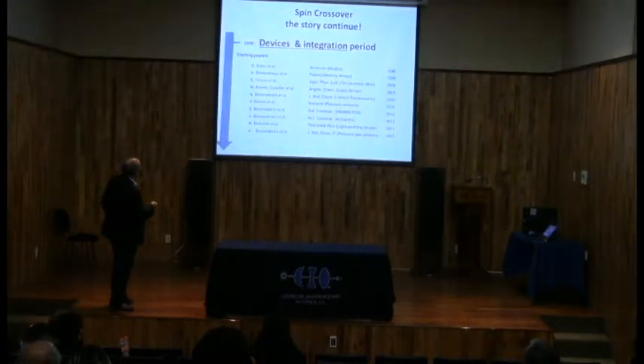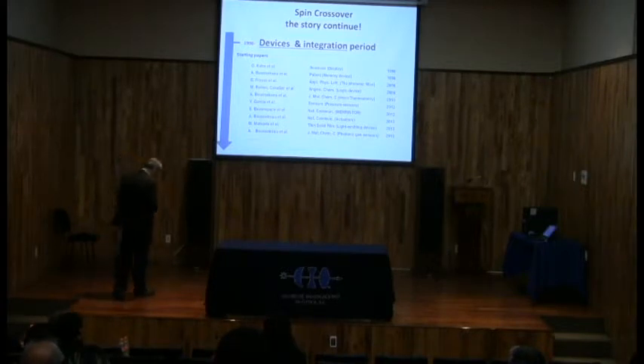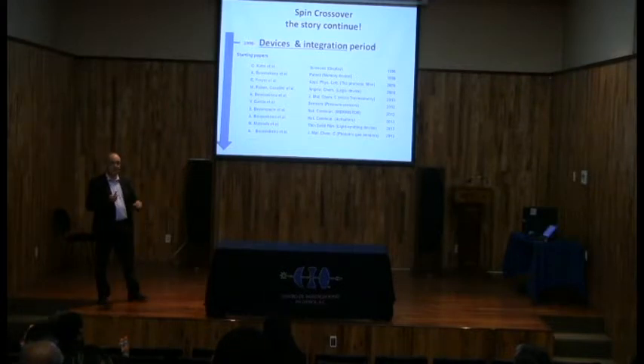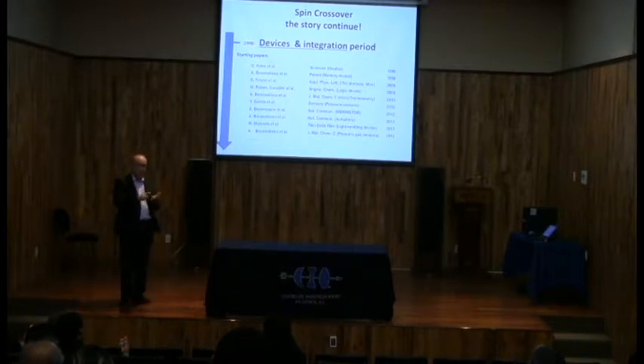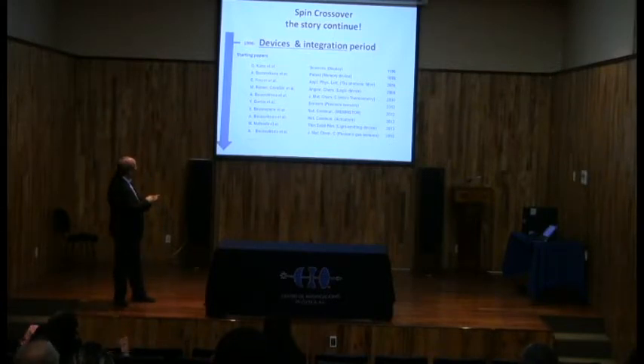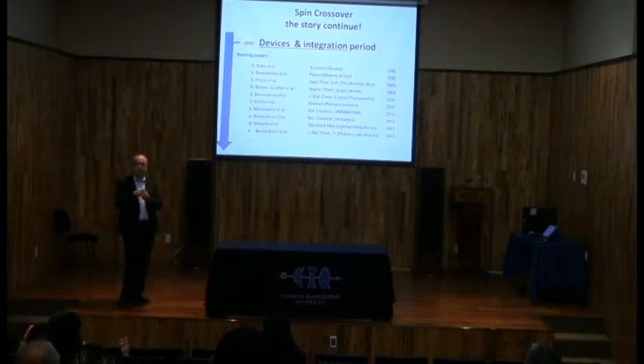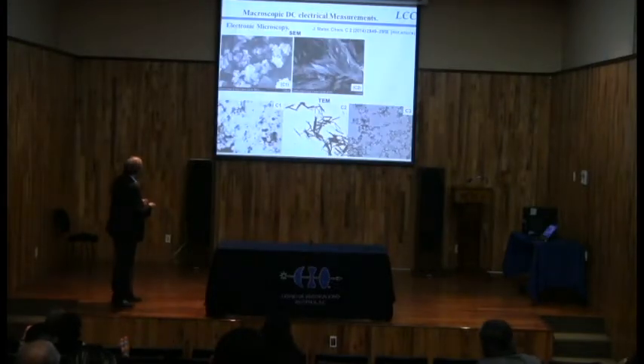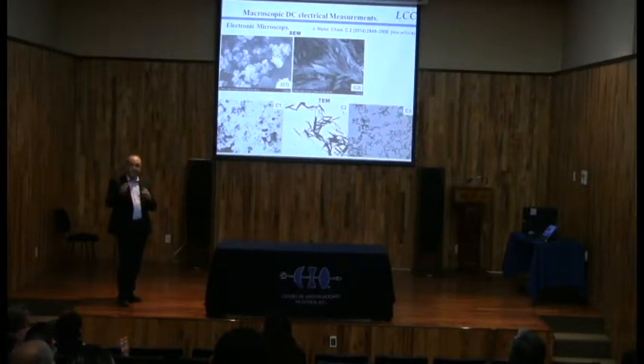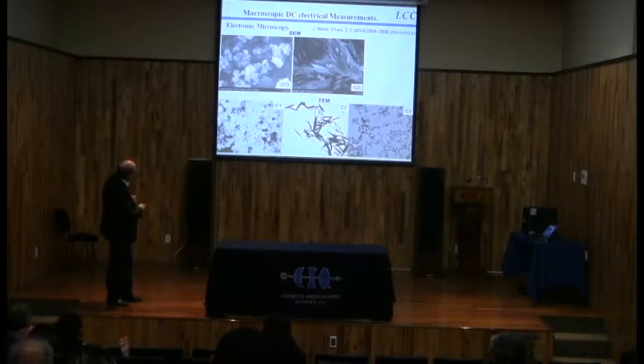Okay? And then, of course, after this, in this field, the device integration started, because as I have shown you, now we have the molecules, we have the films, we have the nanoparticles, we have the way to switch them, okay? So we have the thin films, which is quite important, and we wanted now to use these materials in devices. As I told you before, by playing with the concentration of micro-emulsion techniques, you can have nanoparticles, and then you can play with the shape of the nanoparticle. You can have squares, you can have even rods like that, okay?